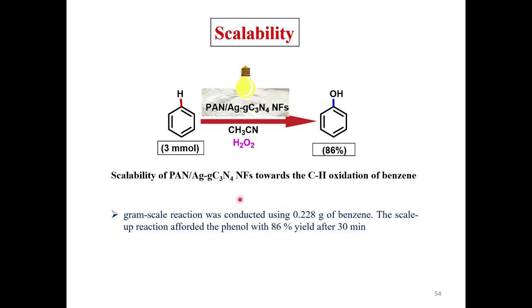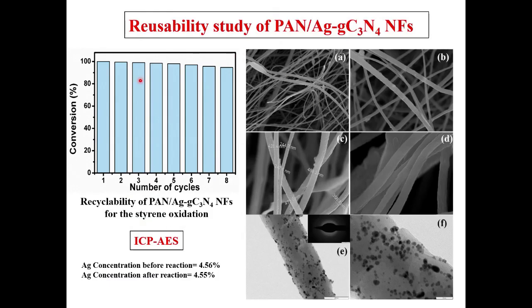Means we have done the scalability of PAN-Ag-gC3N4 towards the CH oxidation of benzene, 3 millimole, with 86% of the product obtained. When we go with the recyclability study from first to eighth cycle, there is a marginal decrease in the percentage of the product. And when we have done the ICP-AES study, it is observed that the silver concentration before starting the reaction is 4.56%, and after the 8th cycle it is 4.55%, only 0.01% leaching of the silver from the surface of the particle is observed.